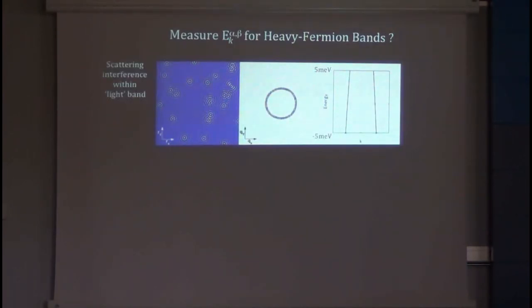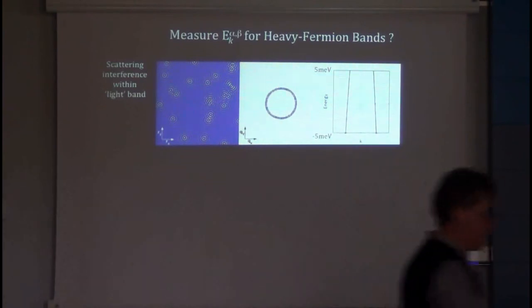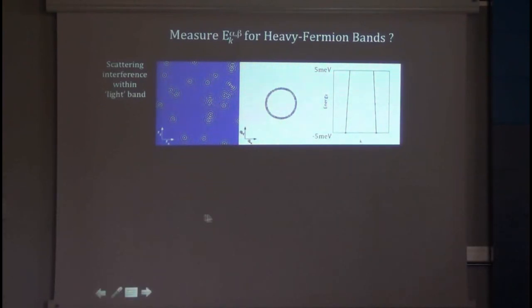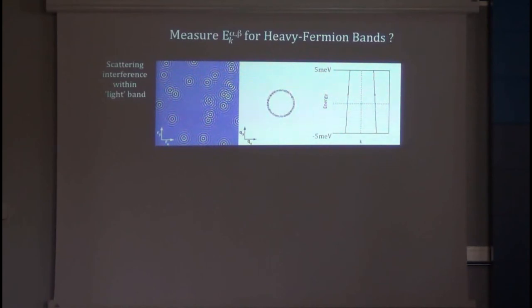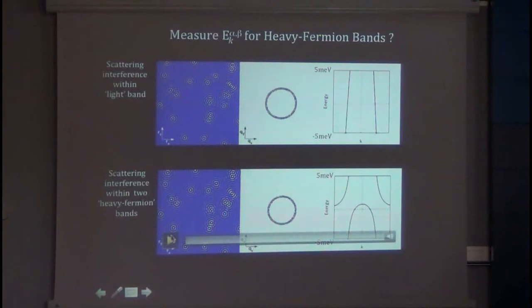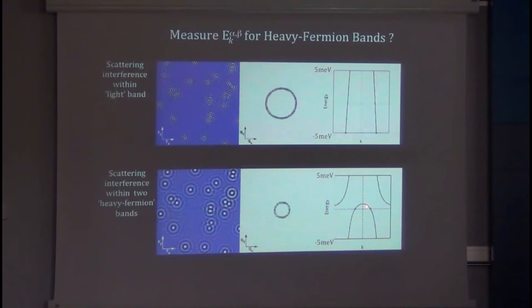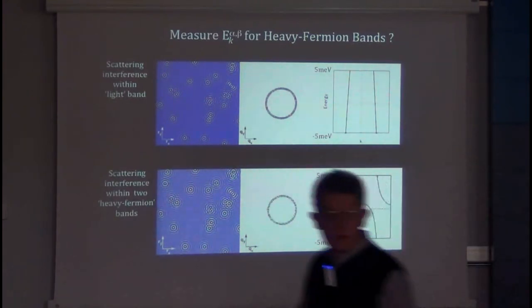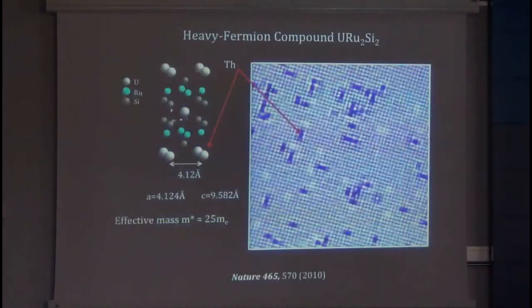Okay, so scattering interference I already showed you from light electrons should do something like this. You're only changing the energy by a few millivolts here, so virtually nothing should happen. Very slowly changing wave vectors. On the other hand, if you have heavy fermion physics, you should expect huge effects. Because when you cross the chemical potential, the band structure suddenly jumps to a completely different wave vector. That's what we were looking for in the design of the experiment.